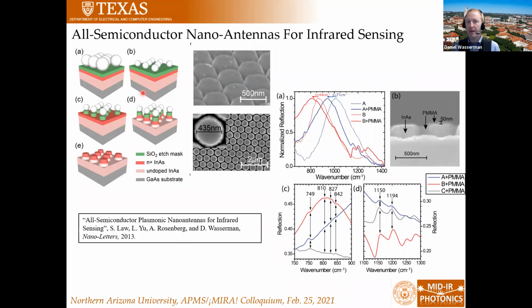So we can make, for instance, nano antennas now, right? So I said we wanted to take micron scale wavelengths nano. We can generate these localized surface plasmon resonances, and you can see they're rather significant resonances that we're observing here. Distinct features associated with sub-wavelength plasmonic particles fabricated from doped semiconductors operating in the mid-infrared.